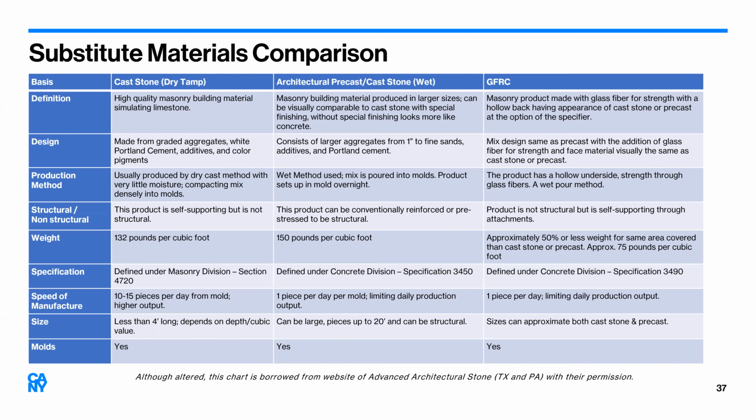Back to the substitute materials, do you see any adhesion problems with mortar or sealants when using them? Yes. The resin-based materials, you have to use a primer before you point with a standard mortar, because a standard mortar without that primer, either in the mortar or on that substitute material, will not stick. And truthfully, your fabricators should warn you, and you should ask them, do I need a primer?